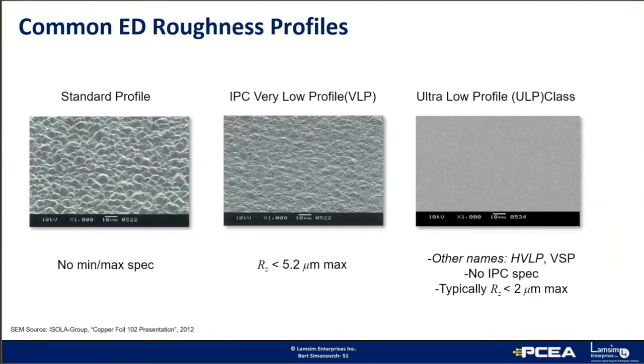There are three common foil roughnesses used in the PCB industry today. The most common is the standard profile and has been used for years. It has no minimum or maximum roughness spec, so the rougher the better to meet the peel strength and other requirements. But as roughness became an issue with signal losses, IPC came up with a very low profile, or VLP, spec. The VLP foil is typically any foil with a roughness of less than 5.2 microns.